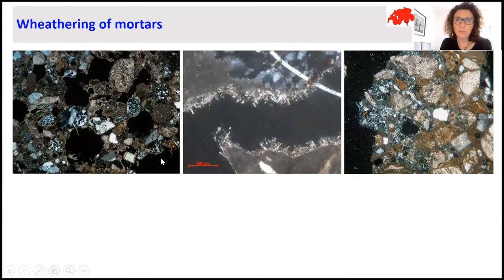With the microscope it is also possible to understand and study the mechanisms of decay. For example, here we can see that this mortar with very large pores has some processes of dissolution, and here, at a higher magnification, a recrystallization of the calcitic binder. This is because an air lime is not made for being in long contact with water, because calcium carbonate has low, but some, solubility. So the binder can be taken away, increasing the porosity, and we can also have secondary crystallization of calcite around the pores. It's also possible to observe a secondary process of sulfation, for example, the transformation of the calcium carbonate into calcium sulfate because of sulfation and weathering processes due to an aggressive environment.